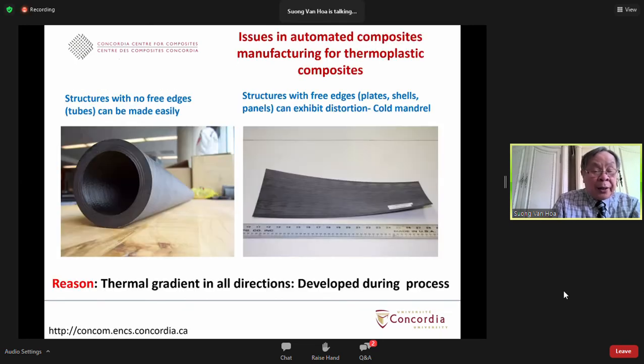Now, we identified two kinds of structure. One is structure without free edge, such as the case of a cylinder like this. For this cylinder without free edge, it's no problem. We were able to make them very well, no issues. However, for the structure with the free edges, that means something like a flat plate, or the case where you have a curved panel where the fiber is cut.